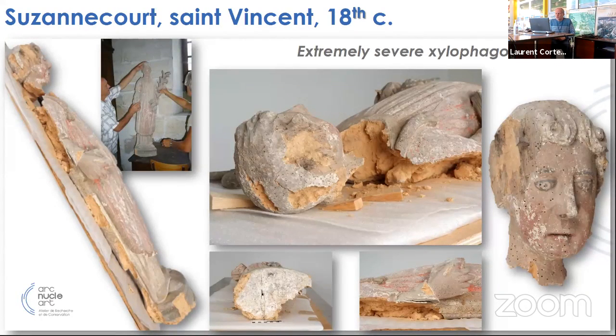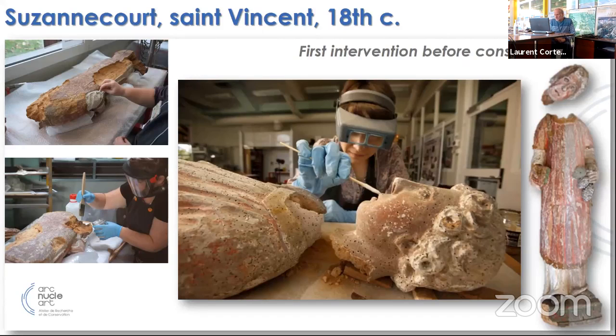Here is the case of an extremely damaged polychrome wooden sculpture that was attacked by xylophagous insects. You can see a lot of powder, and it was really a last chance treatment. Before doing the impregnation, the conservator tried to clean and fix what was possible to do with conventional techniques. It was very difficult because, of course, it was very fragile at that step.